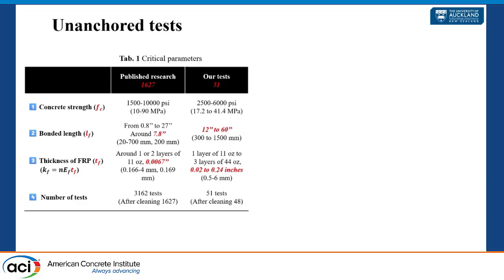Building on that evidence, we got the confidence to move to the second phase of our project. We conducted 51 experimental tests at the Simpson Strong-Tie Stockton Research Lab, with concrete compressive strength from 2,500 to 6,000 psi, bonded lengths ranging from 12 inches to 60 inches, and using 1 layer to about 3 layers, so 0.02 inches to 0.24 inches. After all tests were done, we got valid results from 48 tests, because another 3 failed for unexpected reasons, like installation error.